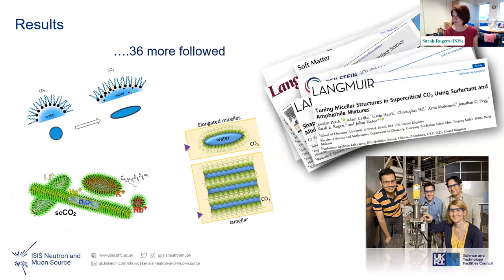So we've done all sorts of tricks. We've changed the surfactant, we've changed the counter ions. It allows us to change the shape of those micelles, from the spherical ones that you saw to more elongated ones. That allows us to do things like playing tricks with the viscosity of the CO2, which can be handy when you're trying to enhance oil recovery or for storage. If you want to store the CO2, it needs to be thicker.